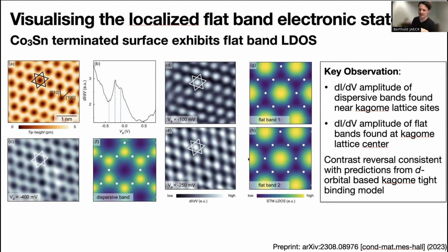By contrast, when we go inside the flatband, even here, the tight binding calculation can accurately reproduce what we have observed in our experiments. Interestingly here, as we saw in our measurements, the density of states of flatband 1 and 2, in this case, I believe this is a dxy, dxz, dyz, and the lower one should be the dx square minus y square flatband. In both cases, the spectral weight is localized in the honeycomb center of the Kagome lattice. So what we detect here is fully consistent with our experiments.